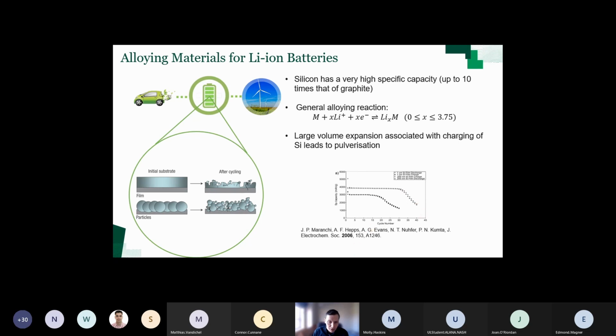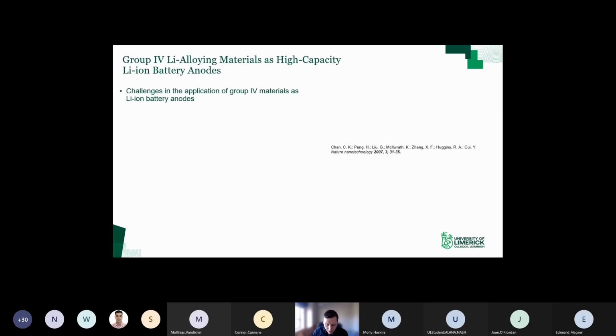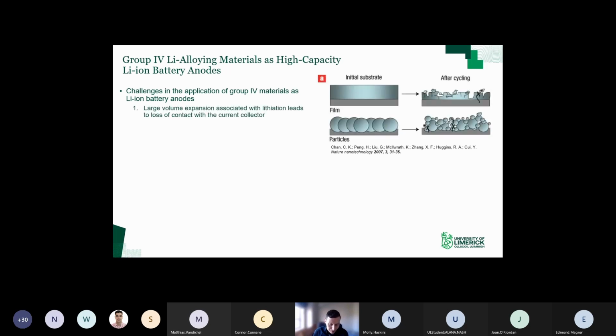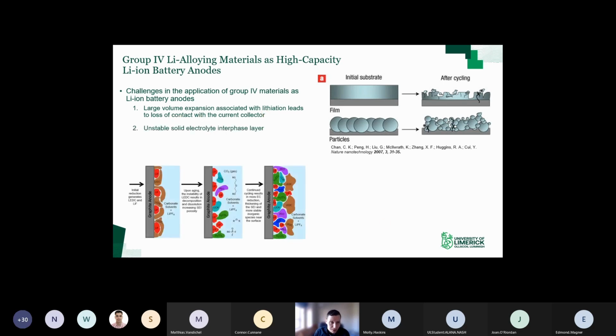Okay, so you have to mitigate that somehow. That's one of the major challenges with the incorporation of an alloying material as an anode for a lithium-ion battery. It's that large volume expansion that leads to loss of contact with the current collector. There are other challenges, and the second one is an unstable solid electrolyte interface layer. I'll talk about what that means in more detail later in the talk.